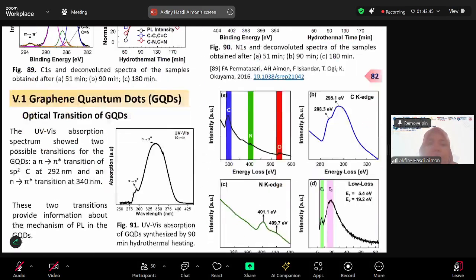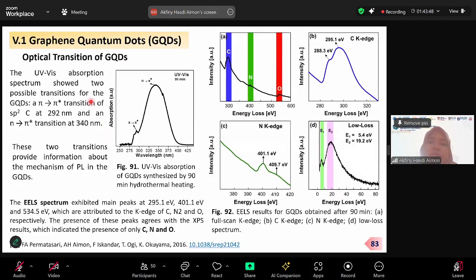Okay, and then this is the optical configuration. You see the contribution of carbon, nitrogen, and oxygen here. And the EELS spectrum exhibits main peaks at 295, 401, and 534 eV, which are attributed to the K-edge of carbon, nitrogen, and oxygen respectively. So it's an indication of carbon, nitrogen, and oxygen in our sample based on the EELS spectrum.